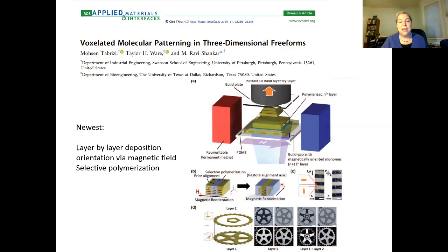But each of these patterns, again, represents a program, not just for an initial shape and a final shape, but a complete choreography of motion when the material is stimulated. And as I showed at the beginning, you can stimulate the shape change by a change of temperature. If the material is doped with the azo dye, it can be actuated by shining light on it, or it can be done with an electric or magnetic field, depending on what the material is sensitive to. And one of the cool things about that is that even the stimulus doesn't have to be uniform. You can shine light selectively on the sample, or shine light on one side and not the other side. And so all kinds of programmed motion are possible.